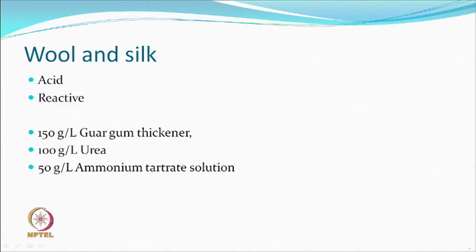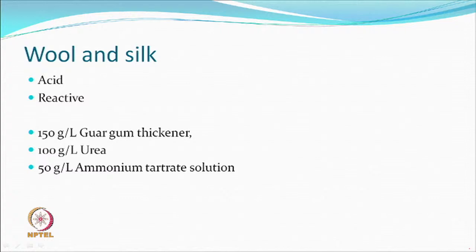For wool, acid dyes can be used — which is the normal case for wool and silk — because the color gamut available looks pretty good. Reactive dyes can also give similar effects, but acid inks are available specifically for wool and silk. If using acid inks, you will not use alginate, because in an acidic environment it coagulates and causes difficulty. One interesting thickener that remains usable is guar gum. You do control molecular weights so that during washing later you should not have difficulty.